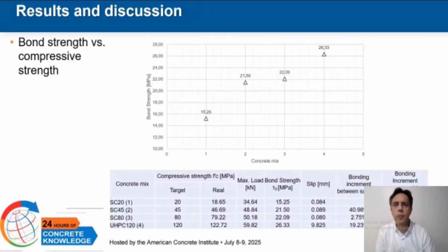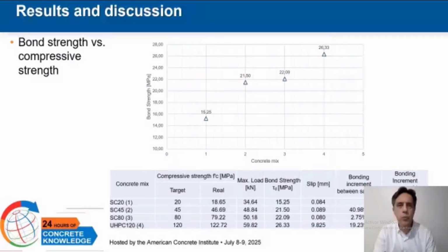This table and graph summarize the average compressive, bond, and slip strengths of each concrete mix tested under the RILEM RC5 configuration. As expected, there is a strong correlation between compressive and bond strengths. The SC20 mix produced a bond strength of 15.25 megapascals with a measured compressive strength of 18.65 megapascals. Bond strength increased to 21.5 megapascals in the SC45 mix, around a 41% increase compared to the SC20 mix.